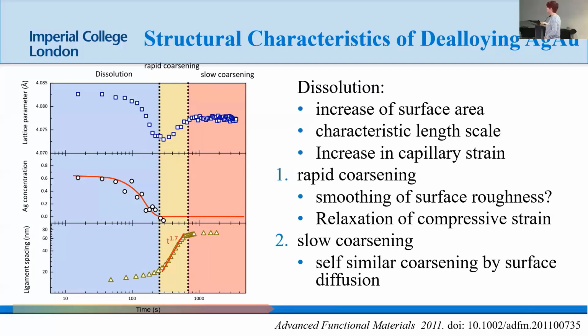So we see a characteristic length, though. It's self-similar coarsening. They all do the same thing, regardless of what concentration we're sat at. The time scale might be different, but it's self-similar. And it's driven by the surface diffusion.